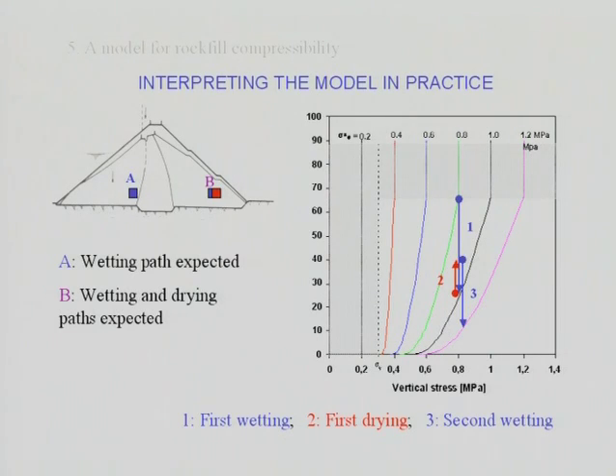Now it's interesting to interpret these ideas in a real problem. For instance, this is point B in the downstream shell of the dam. And what are the paths that nature is actually inducing in this point? You build your dam, and then you are perhaps in a point such as this initial point here, and then some rain comes, and it will induce some wetting at a constant total stress. Then you will drag your yield curve towards this second point here, and in doing so, you will move your yield curve towards the right. That implies irreversible deformation. This is a collapse.